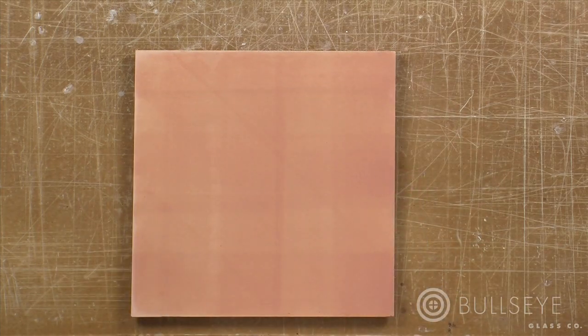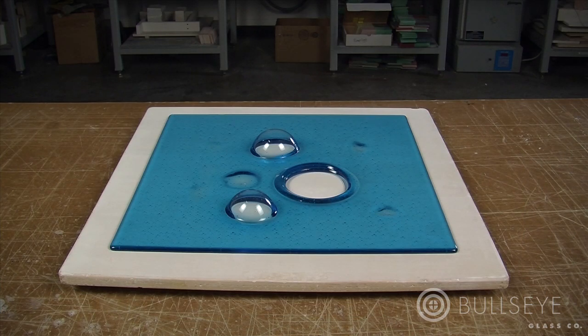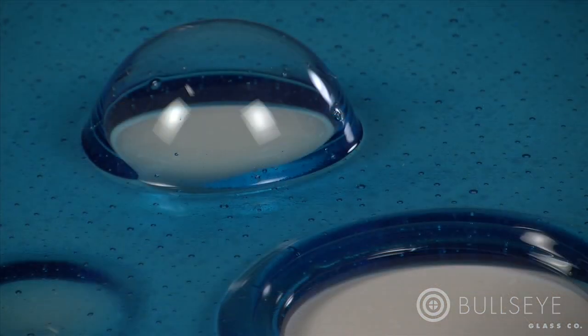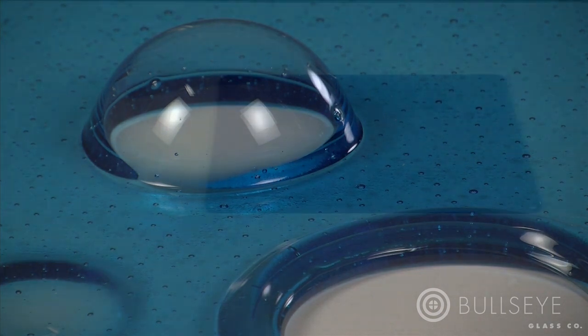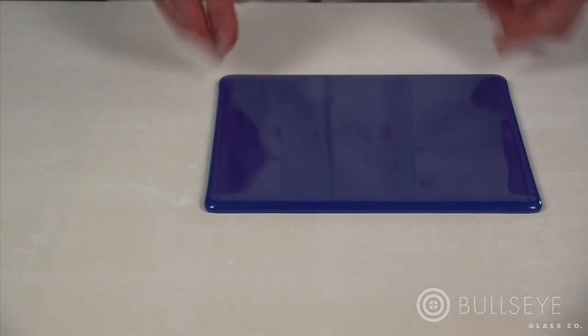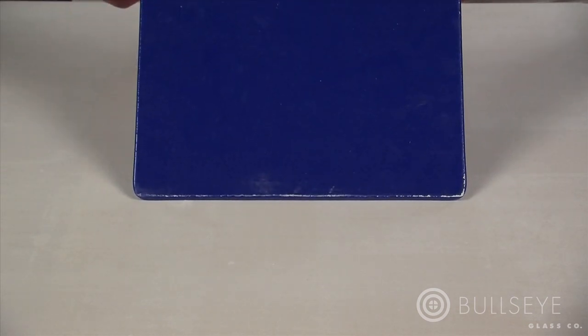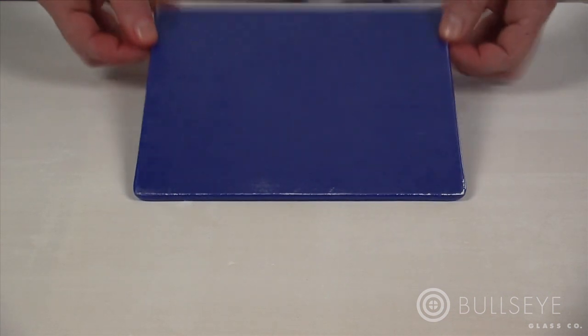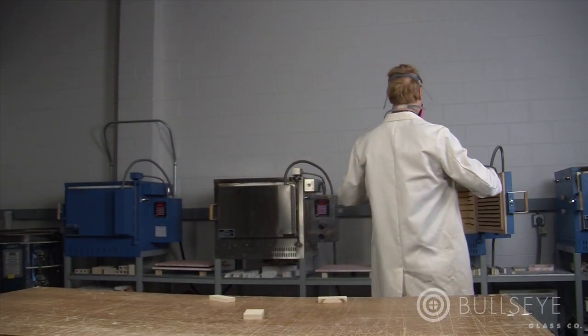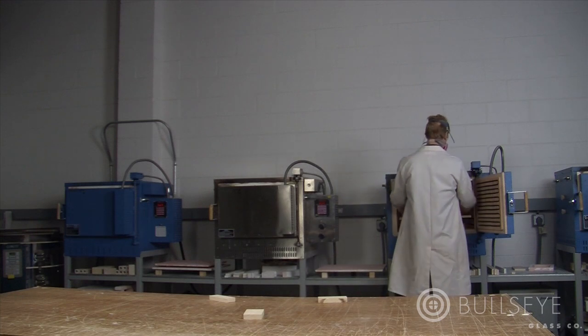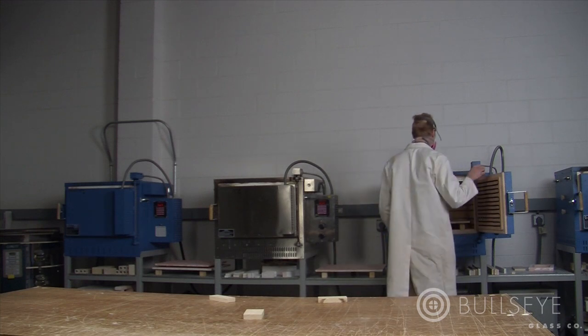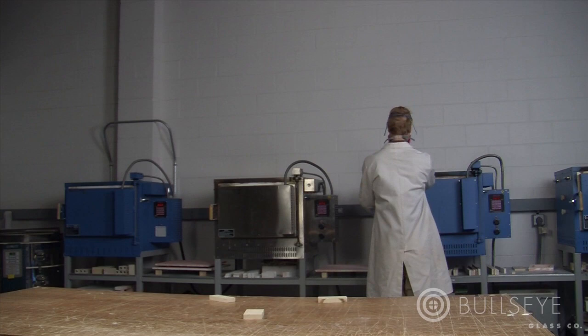Upon firing, a damp shelf will release moisture that can get trapped beneath the glass. This will turn to steam at fusing temperatures and create a bubble or bubbles in the fired glass. A wet shelf can also cause small needle points to form on the perimeter of the piece, and it can cause primer to stick to the glass, potentially affecting the surface. These problems are easily prevented by thoroughly drying the shelf in the kiln. Shelves that appear dry to the touch may still hold moisture.